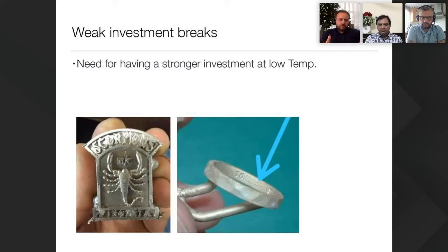So first of all, if your investment is weak, depending on the expansion movements happening between the resin and the investment, you will have resin breakage, like these cases on the left, which you usually see on the engravings. I mean, Dipen, maybe you have some experience on that. Yes, true. So the first thing we want, ideally, is to have a strong investment.